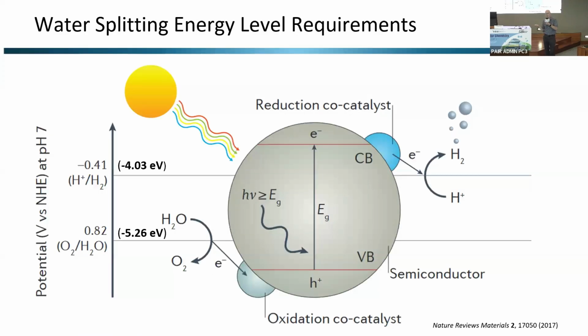So if we look a little bit more into the properties required from a semiconductor in order to drive these electrochemical reactions, you can see this quite clearly here. So this is a wide bandgap semiconductor. As I mentioned, light is incident. It promotes an electron from your valence band, if you're a physicist, to your conduction band, if you're a chemist, from the HOMO to the LUMO. And somehow we're generating free carriers, or they're splitting at this heterojunction with our co-catalyst here or here. And then we can drive oxidation and reduction.